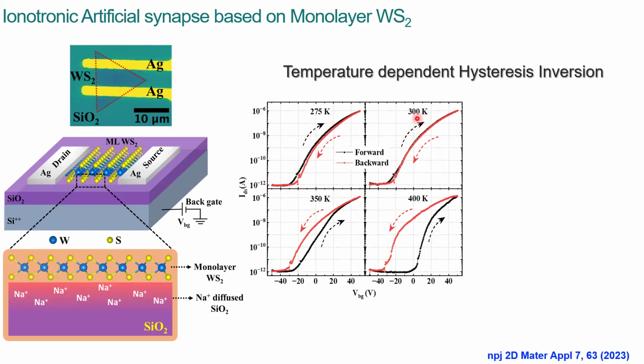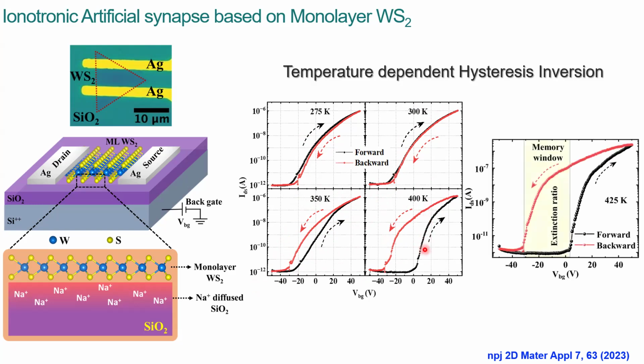But if you see at room temperature, it's completely overlapping the back and forth. But if you see here, there is a difference between this sweep and this sweep. So this is a counterclockwise direction. If we sweep from minus 50 to plus 50 volts, the black curve is the first sweep. Then while sweeping back, it increases the conductance. And if we go on increasing the temperature, the memory window also increases. We have not gone very far because we have to test the device for a number of attempts, so we just stop around 425 Kelvin. And here you can see there is a huge memory window.